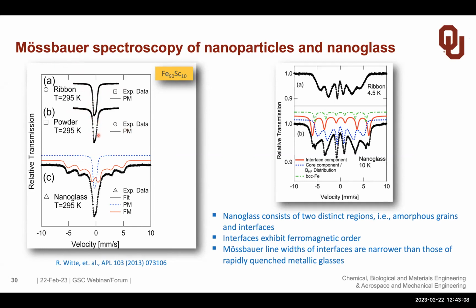And you see the spectra, they look identical, because in both cases, the powder and the ribbon was quenched quickly or fast. So once you take that powder and you compact it, what I described earlier, I showed you in that video, you see the spectrum changes dramatically. First of all, there is still a component shown here in blue, which resembles this here. So that's the fraction which is rapidly quenched. But the other one, which is a 6-line spectrum shown here in red, first of all, it indicates that it's magnetic. That's why it has 6 lines.